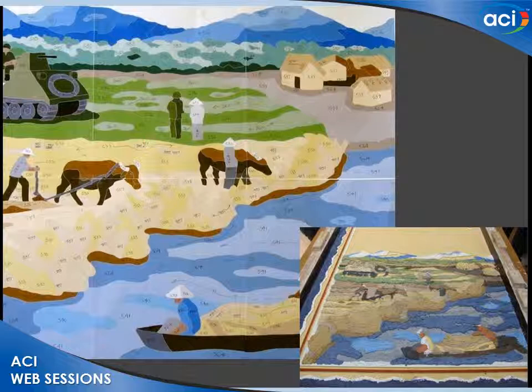And the lower right, you can see as it's progressing, the lines between the colors start to get blurred because the first mix that goes in, you have to keep it below the top of the ridge. The second mix goes up over the ridge and over the first color so that you have some thickness to that color coat. Because when you expose the ridges, you don't want to show the backup mix where the ridge is.